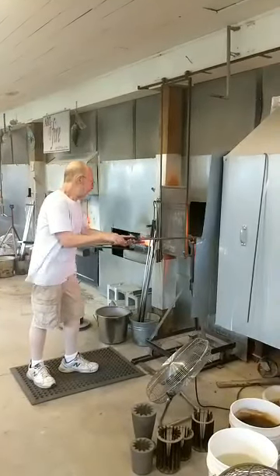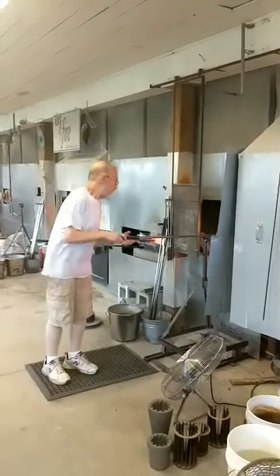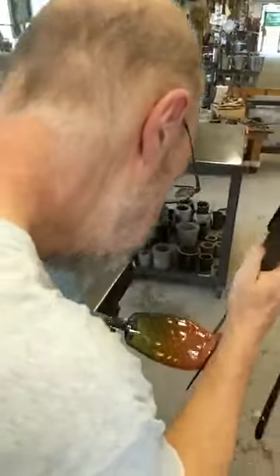So anyway, when we put the glass away at maybe 1,300 degrees and it falls to 900, it's safe. When we turn the annealer off at 900 degrees, it'll take a full 8 hours to get down to room temperature, and that's where the critical temperatures are to avoid cracking. We're going to avoid the cracking.